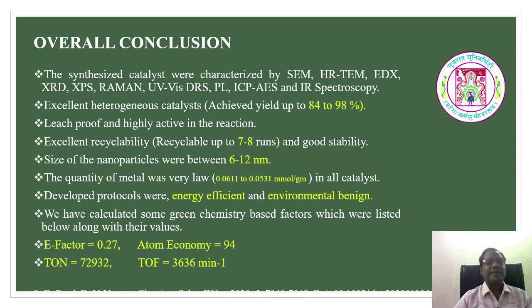Now here I can conclude this session. We have synthesized the different nanocatalysts like Ag nanocatalyst, copper nanocatalyst, and the palladium catalyst, and that catalyst is doped in the different supports, and the synthesized catalyst is characterized by the various techniques like SEM, HRTEM, EDX, XRD, XPS, and IR spectroscopy. It was found that the heterogeneous catalyst was utilized and yield was achieved up to 98%.